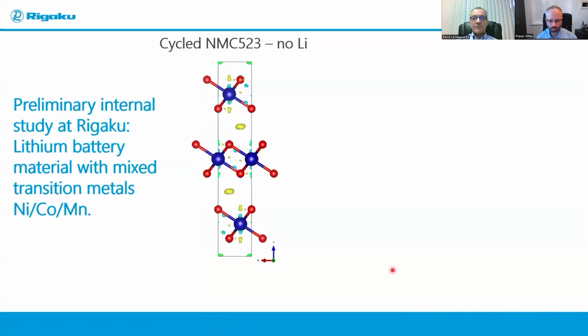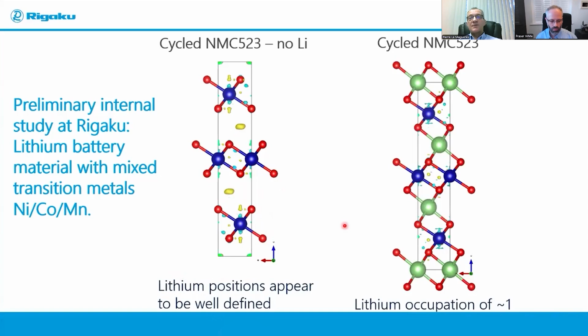So on our own, we've done some preliminary studies at Rigaku on battery materials made of a mixture of nickel, cobalt, and manganese. And these are the blue spheres shown on that picture. The red spheres here are oxygen atoms. And it turns out that once we can solve the structure of the main framework made of the metal sites and the oxygen sites here, the electron coulombic potential map shows basically maxima for the lithium atoms, and these are those little blobs that you see between the oxygen atoms. And so those suggest that the lithium positions can appear well defined. So this material used lithium atoms, not sodium. Okay? And so it turns out that once we place the lithium atoms at these maxima, the full model could be successfully refined using a program called Olex2 or JANA2020. But again, Joshua will tell us more about that.